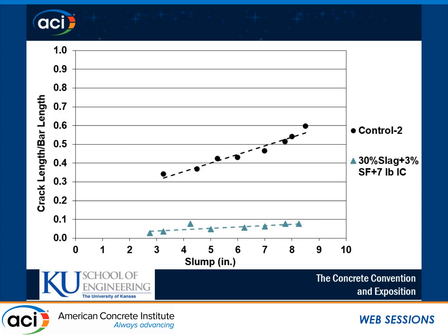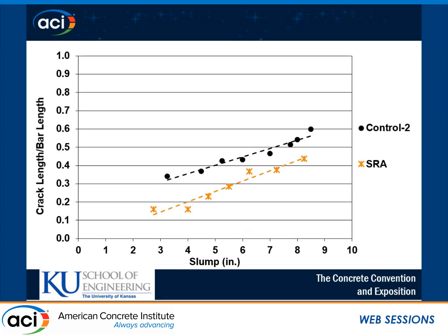And finally, when we add 7 pounds per hundredweight to our ternary mixture, we also have a very low resultant settlement cracking result. And for that same control, when we dosed a shrinkage-reducing admixture, we used a dosage rate of 2% of cementitious materials by weight. And this is for 100% Portland cement. We also see a reduction in settlement cracking. This is likely due to, at early ages, SRAs causing swelling in the first 24 hours.